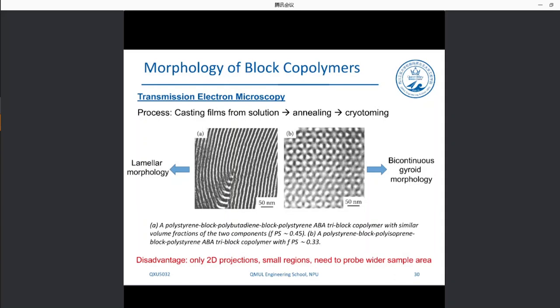The most direct method for the visualization of these phase domains in block copolymers is transmission electron microscopy, or TEM. You probably have heard already about transmission electron microscopy. I will not give you more information, but if you want, let me know. I can provide some information. Usually in this case, specimens are prepared by casting film from solution, and then we produce this equilibrium morphology, which is then ultramicrotomed to create ultrathin sections. In order to do this, in cryomicrotoming, we use cryogenic temperatures.